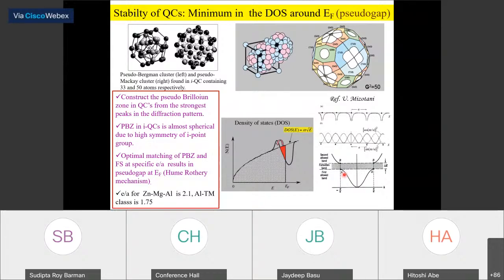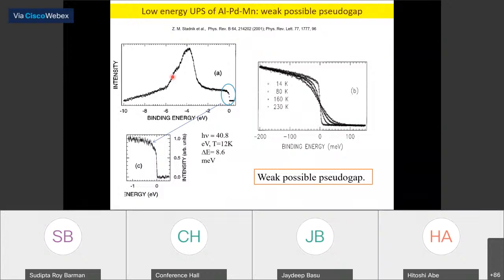which comprise the quasicrystals. But the pseudo gap has been predicted theoretically, and when we did low energy photoemission, we did some work earlier, and there is work from other groups also. What was found is that near the Fermi edge, this small dip was assigned to a pseudo gap. But if you look at the temperature variation of the Fermi edge, one found that it is actually a clear cut Fermi edge, like a metallic Fermi edge. So there was a hint of a weak possible pseudo gap.